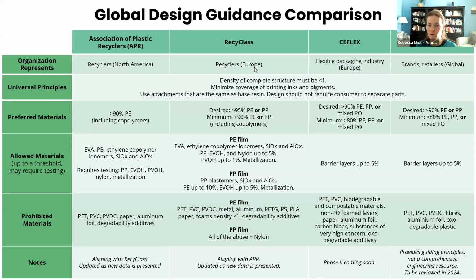Okay, so preferred materials, APR is going to be polyethylene only, because that's really the well-developed consumer recycle stream here. In Europe, Recyclass has standards for polyethylene and polypropylene, as well as test methods around both of those. So they're also kind of zeroing in on those two materials. And then both CEFLEX and the GDRs are really stressing preferably mono PE or mono PP, but they do allow mixed polyolefins for both of those, right? And you can see the percentages there, very standard to what we've been talking about all along.